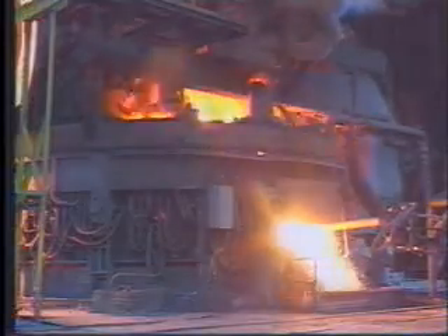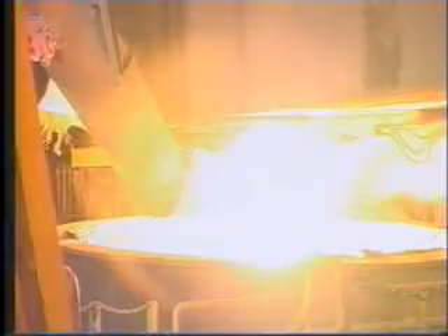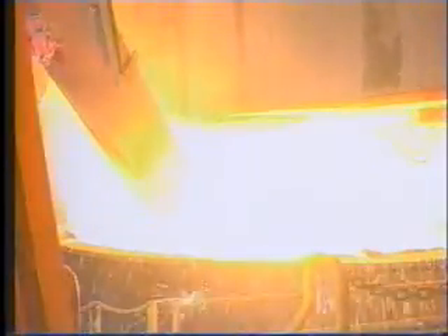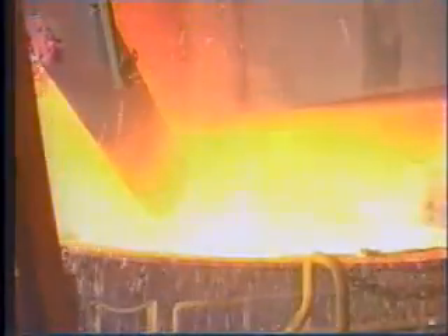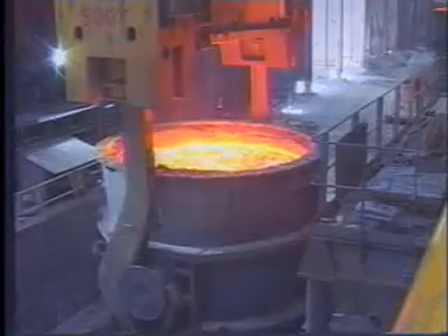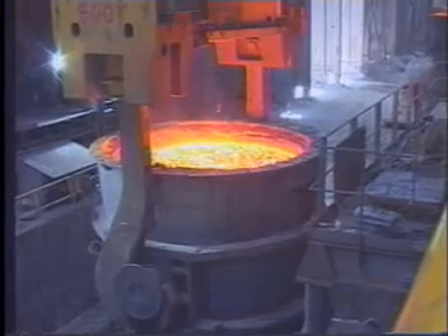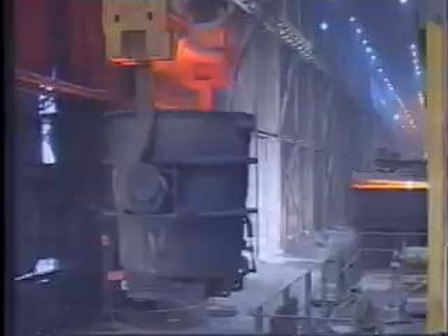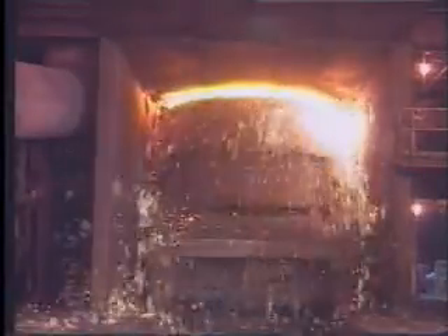Once the heat of steel has been completely melted and the bath has achieved an optimum temperature, it's poured from the furnace into a ladle. The ladle is then transported to the secondary refining furnace, where all of the elements will be optimized to be within specifications. Impurities are removed from the steel by means of bubbling argon gas through the ladle.